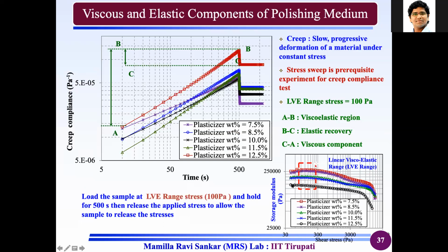Storage modulus is nothing but energy storage inside the polymer molecular networks. As I am increasing my shear stress, there is no change in storage modulus up to a certain point, then there is a non-linearity. That means even though I am changing shear stress in this region, there is no change in storage modulus. That means my polymer molecular chains are at original strength and they are not broken. In a non-linear range, it is broken. That means whenever I want to conduct my polishing experiments for fluid, my polymer molecular chains should not break. That means that I can take any value in this linear viscoelastic range, that is called the LVE range.